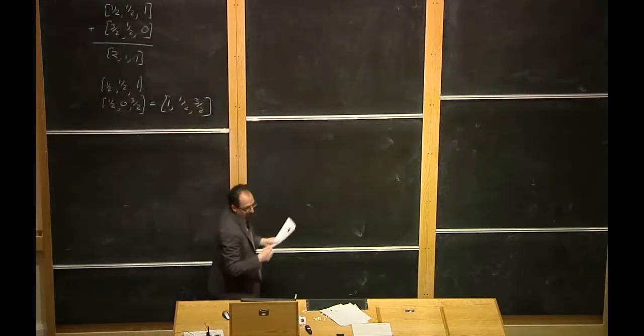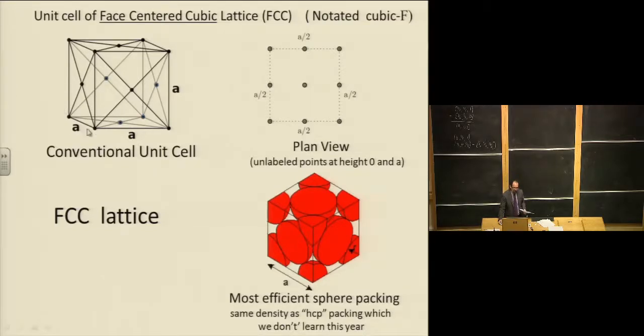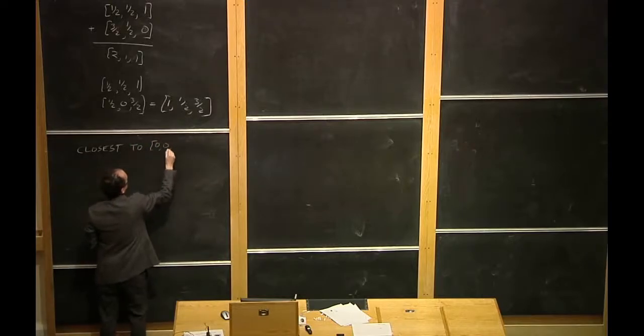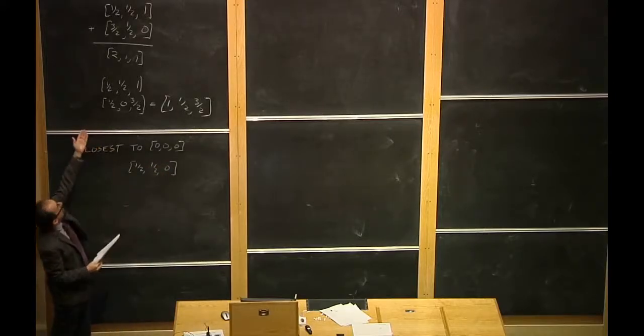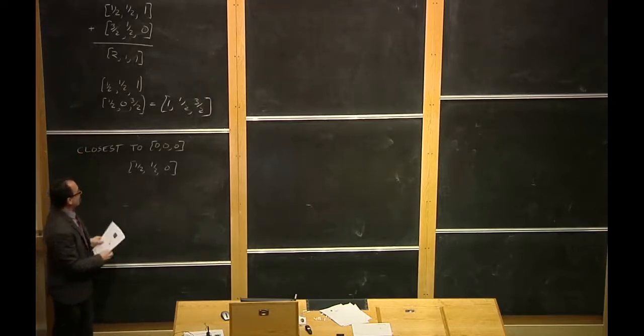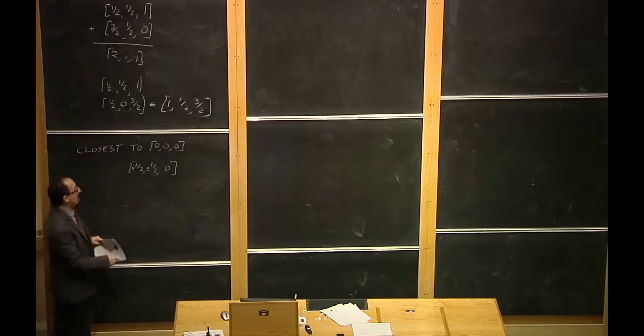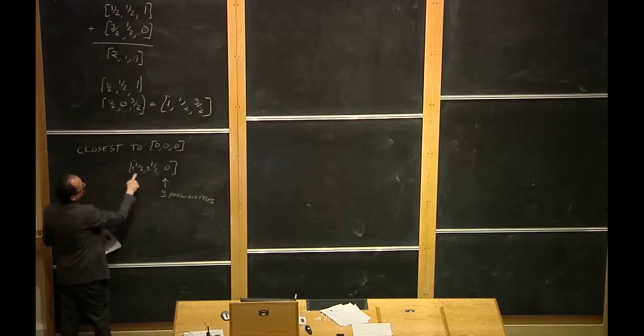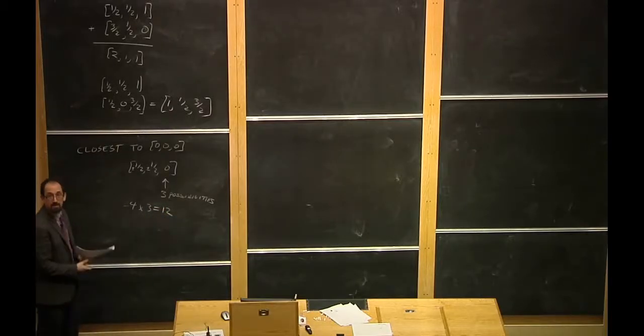The coordination number of the FCC lattice is 12. To see why: take the point at (0,0,0) and look for the closest lattice points. The vector (1/2,1/2,0) fits the definition — two half-odd integers, one integer — and has distance a/√2. We could make each half-odd ± and put the integer zero in any of the three positions: 4 sign combinations times 3 choices of which coordinate is zero gives 4×3=12 nearest neighbors.